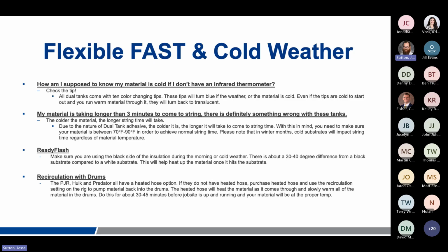So just some other general questions that we get a lot, and I have a couple more of these throughout the slide deck here. What if my material is taking longer than 3 minutes to come to string? That's a call we get a lot. Really, it comes down to how warm your material is and how cold it is outside. Due to the nature of dual tank adhesive, the colder it is, the longer it's going to take to come to string, but also set up. So if you have 40-degree material and you're spraying that out on a 30-degree deck, you could see string time take 10 to 15 minutes, and then you're not going to have good adhesion until an hour, maybe even 2 hours. So it's very important to keep that stuff warm. Again, the ambient temperature and substrate temperature can be 25, but you have to keep that material above 70 degrees, which I know can be difficult in the wintertime. But the harder you try and keep that material warmer, the easier it's going to be to adhere everything.